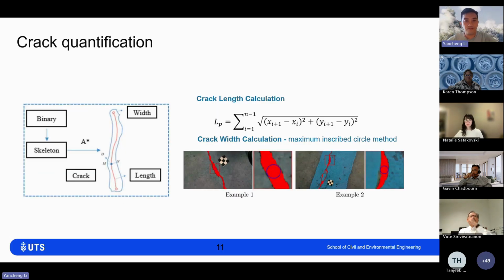This is the process for crack quantification. We first make the skeleton of the crack, the middle line here. Then, based on this skeleton, we can measure the crack length and crack width. We use the inscribed circle method, with small circles, to measure the crack width here.